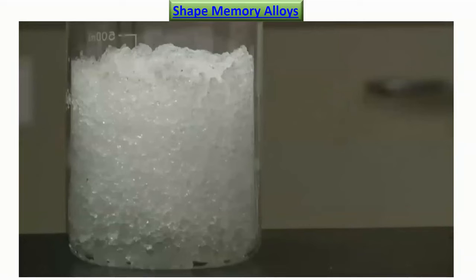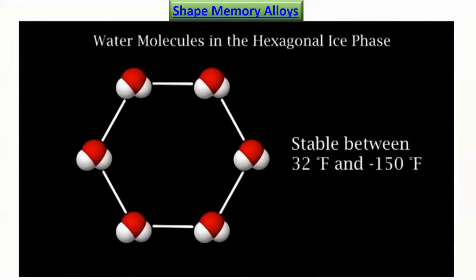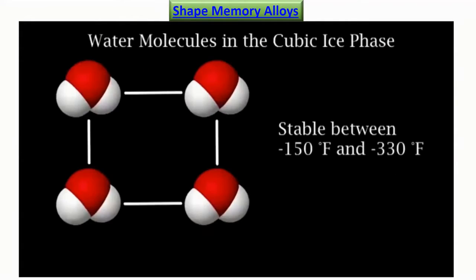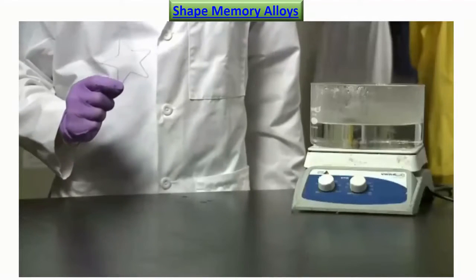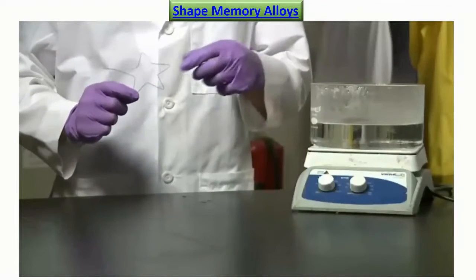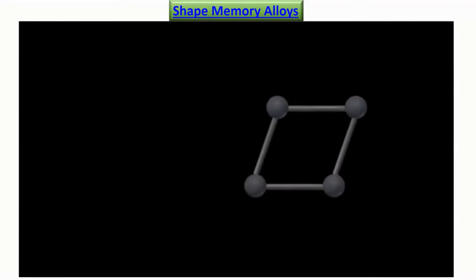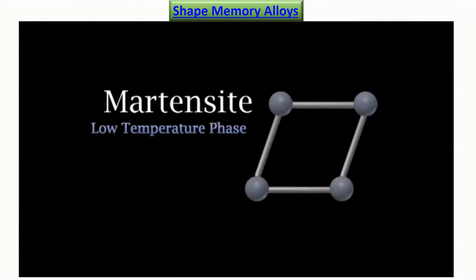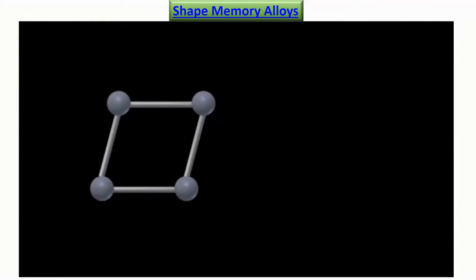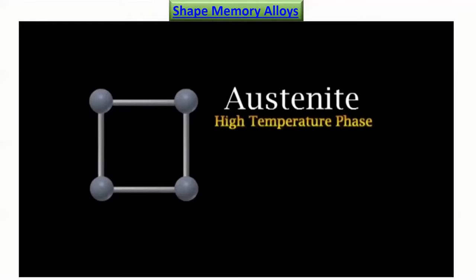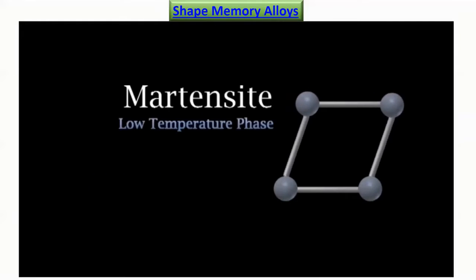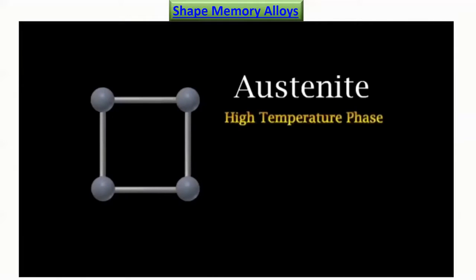But did you know there are actually multiple solid phases of ice? There's a hexagonal phase that is stable until negative 150 degrees Fahrenheit, and a cubic ice phase that is only stable below negative 150 degrees Fahrenheit. So how does this fit into shape memory materials? These materials also have multiple solid phases. There is a low temperature phase that is called martensite. But if we increase the temperature, the atomic alignment changes into another phase called austenite. So at low temperatures, we have martensite, and at high temperatures, we have austenite.